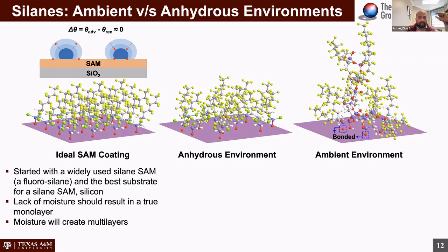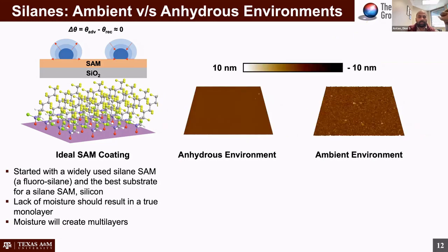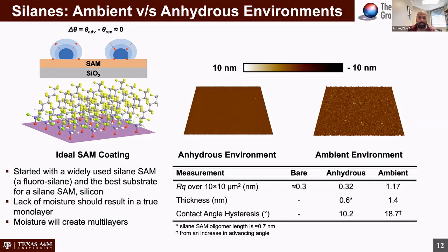Now, to verify this, we coated these on double-sided polished silicon wafers, and just looking at the AFM scans on the surface, you can clearly see the anhydrous environment, your control environment, where there's no water vapor, has a fairly smooth surface. And if you actually look at the data, you'll see that the anhydrous coated surface after coating has a similar roughness as the original surface, but the ambient environment coating, so something that's in an uncontrolled environment, but we did it with anhydrous solvents to make it even, to give it a leg up in a sense, right, over what is typically done. And it still has a larger roughness, it has a larger thickness, and this thickness is dependent on the time that you have it coating in solution.